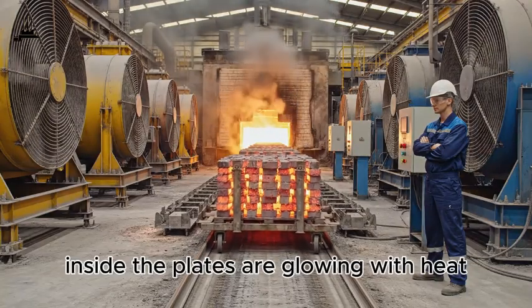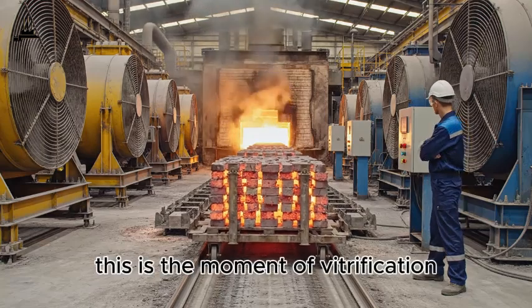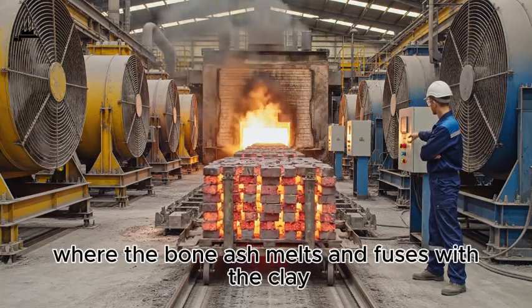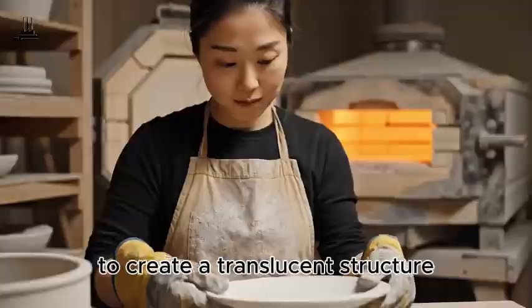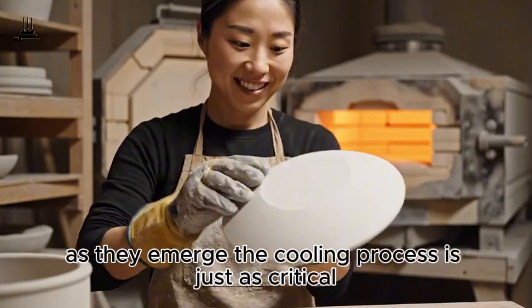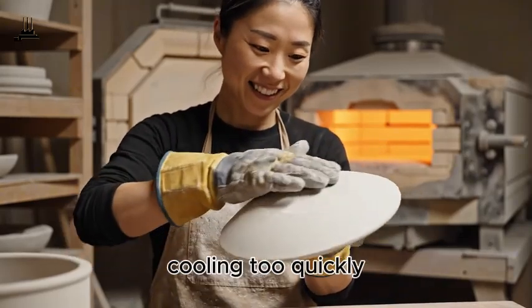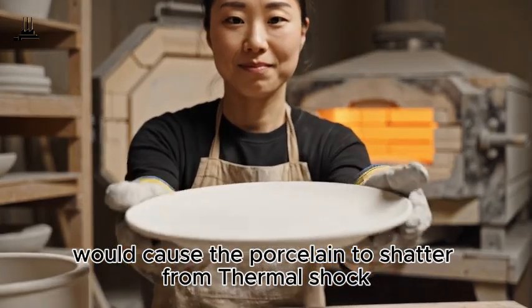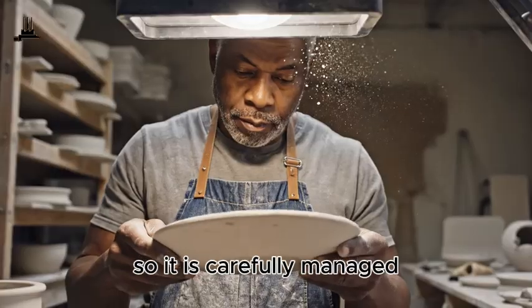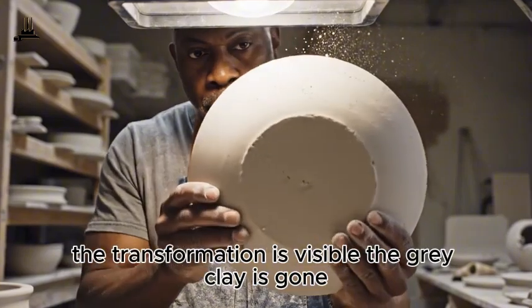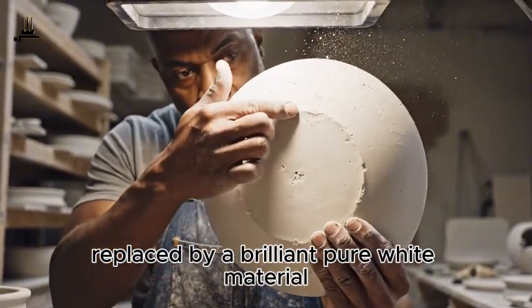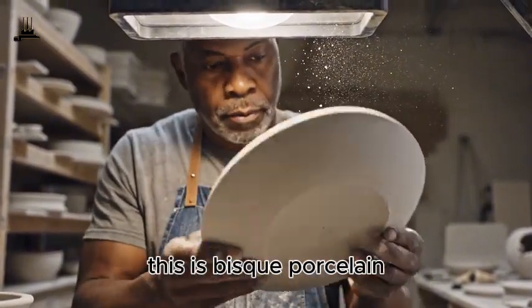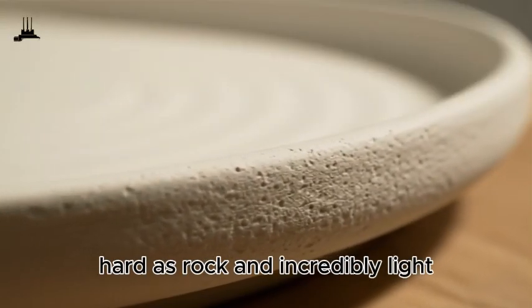Inside, the plates are glowing with heat. This is the moment of vitrification, where the bone ash melts and fuses with the clay to create a translucent structure. As they emerge, the cooling process is just as critical. Cooling too quickly would cause the porcelain to shatter from thermal shock, so it is carefully managed. The transformation is visible. The grey clay is gone, replaced by a brilliant, pure white material. This is bisque porcelain, hard as rock and incredibly light.